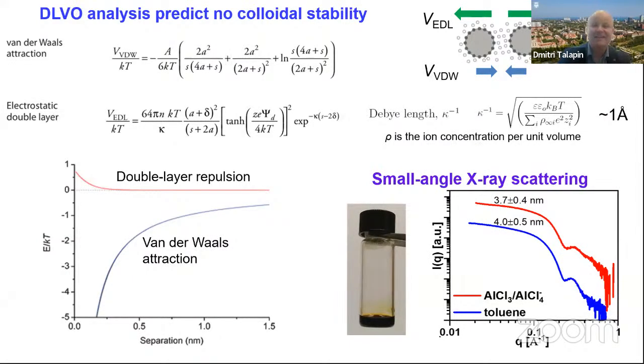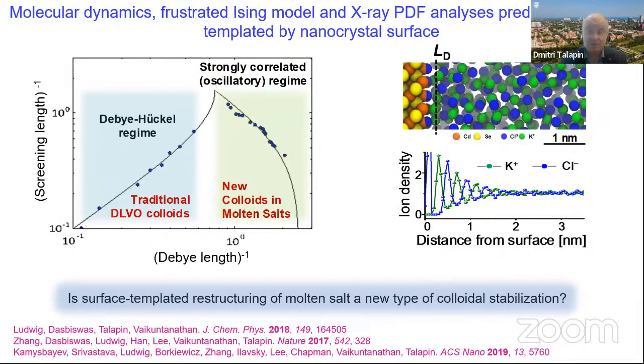But they do exist. In recent years, we have tried to understand what is going on, doing a lot of computational work, hard X-ray analysis and modeling. The picture that is emerging is that in molten salts we have a qualitatively new type of colloidal stability, a new type of pair potentials and interactions between nanocrystals. In dilute electrolytes, we are in the so-called Debye-Huckel regime, where potential drops exponentially into the solution. But in extremely dense, concentrated electrolytes like molten salt, you switch to a different regime based on long-range ion correlations, and the potential no longer drops exponentially but starts oscillating.